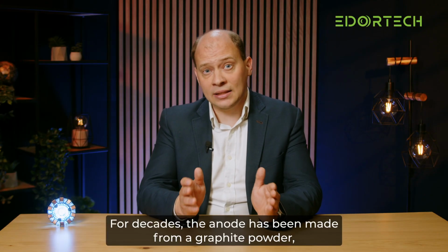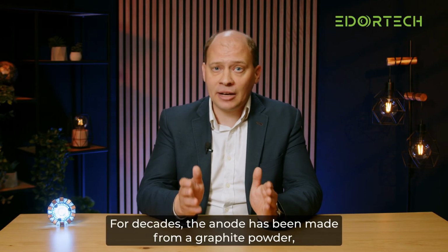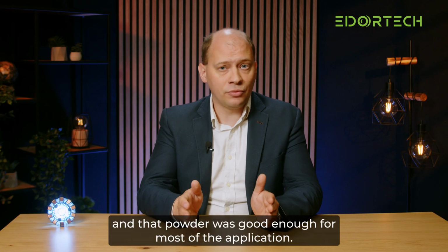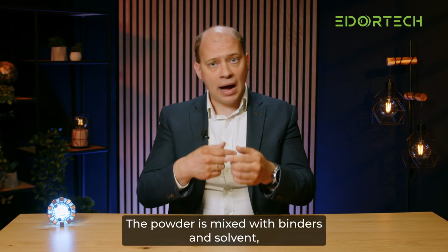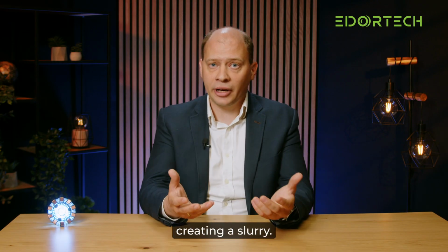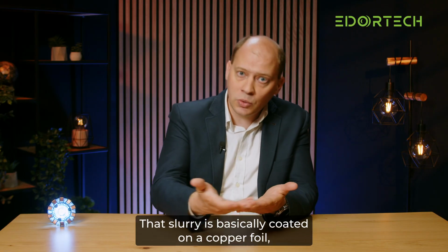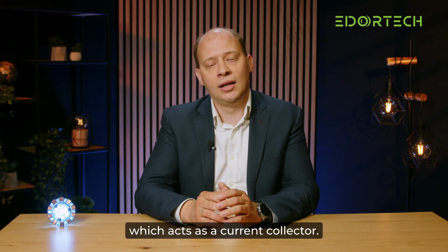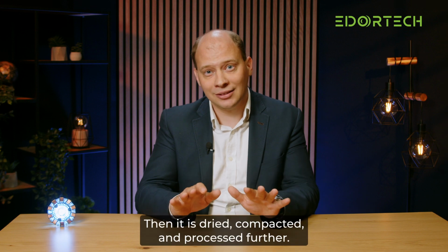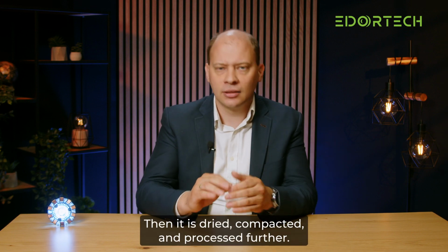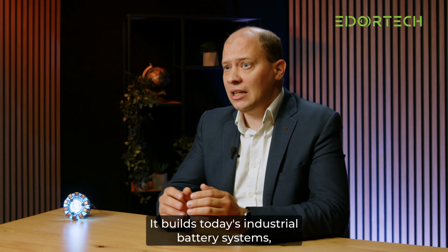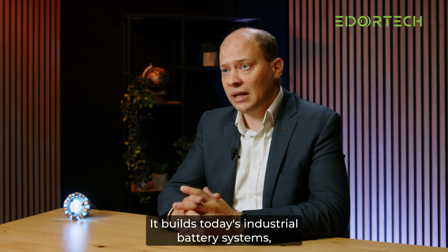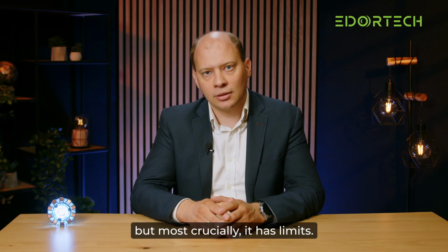For decades, the anode has been made from graphite powder, and that powder was good enough for most applications. The powder is mixed with binders and solvent, creating a slurry. That slurry is coated on a copper foil, which acts as a current collector. Then it is dried, compacted, and processed further. This method works. It built today's industrial battery systems. But, most crucially, it has limits.